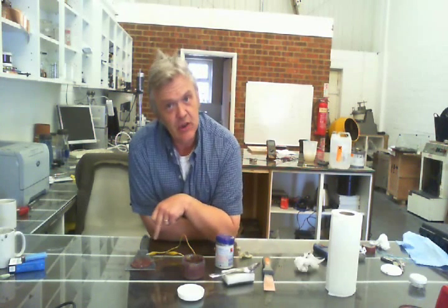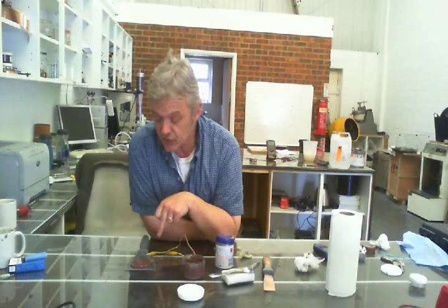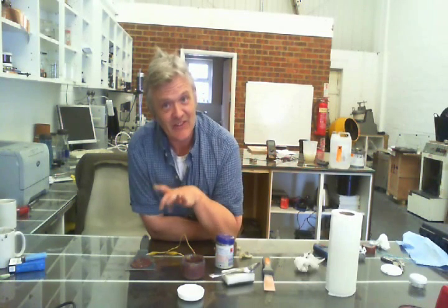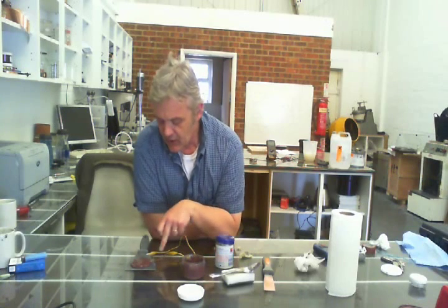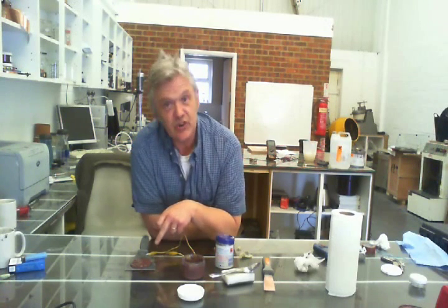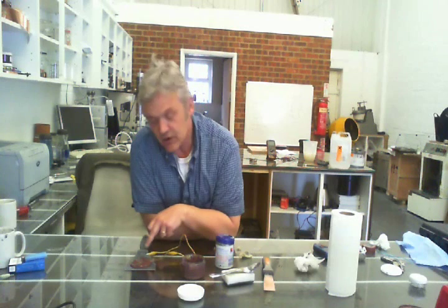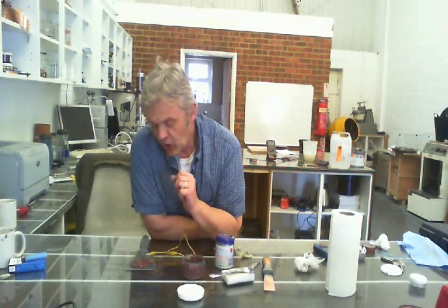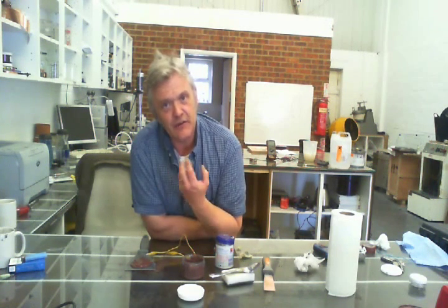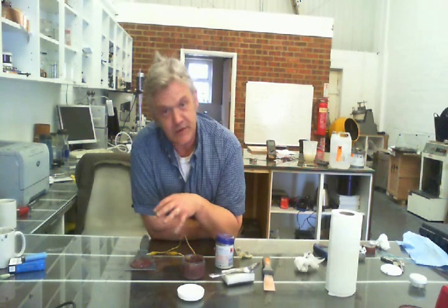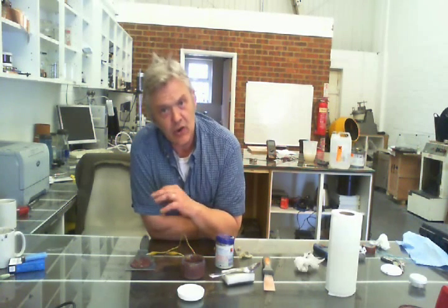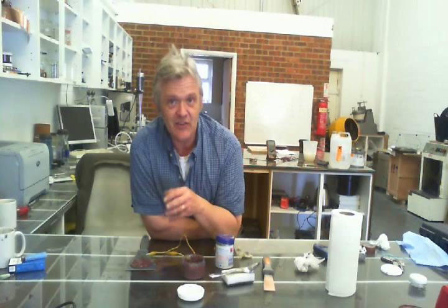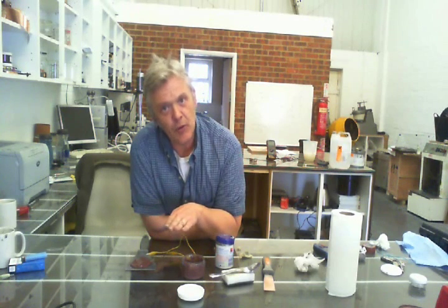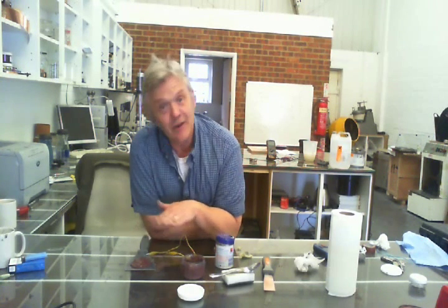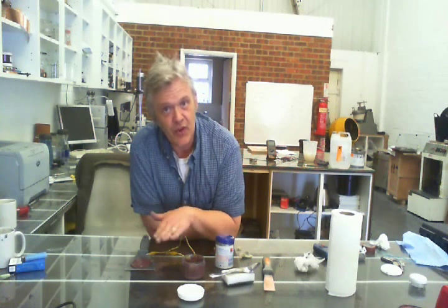But what's happening here is something very, very different. That coppering doesn't stop. Now that's cool. Because the little brush that's in the wire is donating copper ions, and we've got a complete circuit to the steel, and that coppering solution is acting like a kind of gel electrolyte to complete a battery. So that coppering continues on, it's also catalytic. Once there's a layer of copper laid down there, that layer just gets thicker and thicker and thicker.